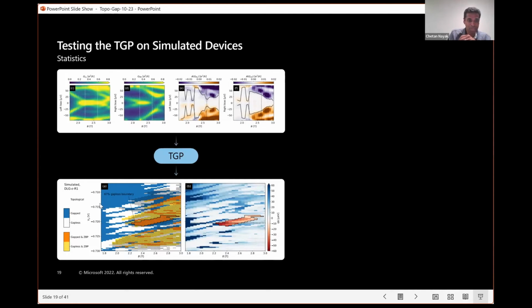These are the gapped regions that do not have stable zero bias peaks. There are white regions, which are gapless and do not have stable zero bias peaks. There are the yellow regions that are gapless and do have stable zero bias peaks. And then there are the orange regions, which are gapped and have stable zero bias peaks. And if those orange regions also have gapless boundaries, then they are strong candidates to be in the topological phase.